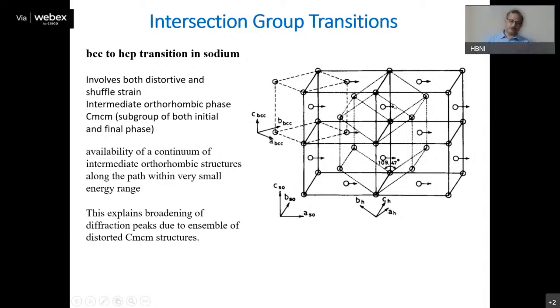And from calculations, it has been shown that for the intermediate orthorhombic phase, which changes the structure from BCC to HCP, the energy differences are very, very small. There can be many orthorhombic configurations along this path, and the energy differences are very small. So in experiments, there is a possibility that you can have an ensemble of these orthorhombic phases. That is the reason when you do XRD measurements, the peaks get quite broad when the phase transition takes place. So this broadening can be explained by the ensemble of the intermediate orthorhombic Cmcm.